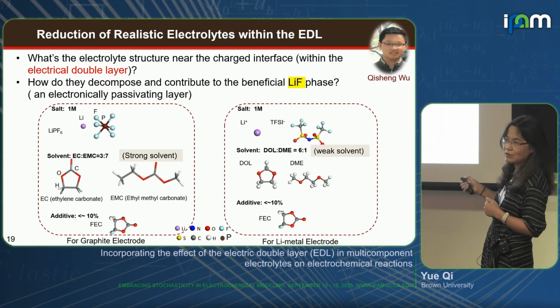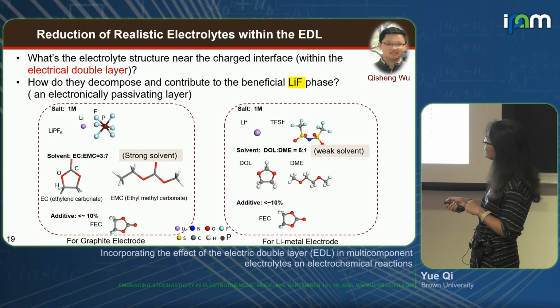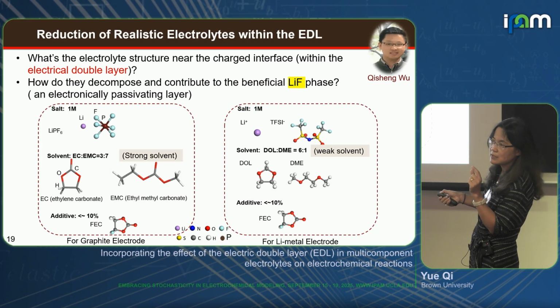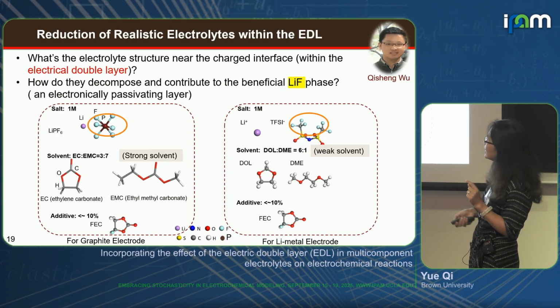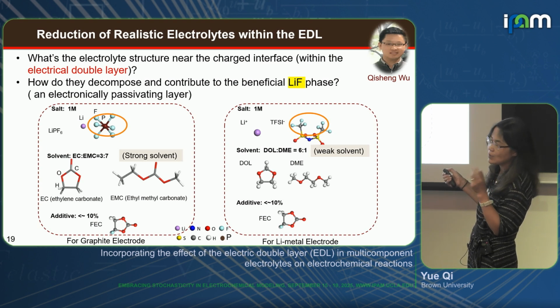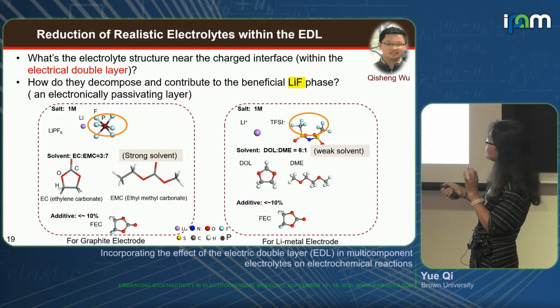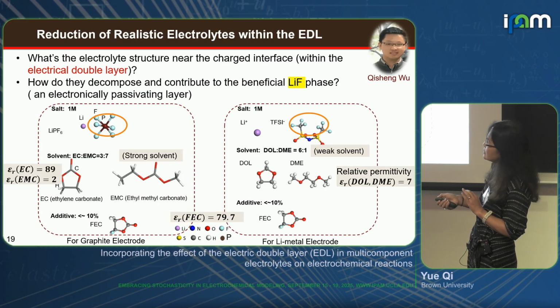What do we think? These are two classical electrolytes. One is used for carbon electrode, one for lithium electrode. And lots of people want to have fluorine species. If you just have salt and the solvent, you notice the fluorine species only comes from the ion, right here. We can talk about why we want some lithium fluoride in these surface layers, but bottom line, we want some fluorine species. These two solvents are very different: this solvent has a really high dielectric constant, and this has a very low dielectric constant, right?